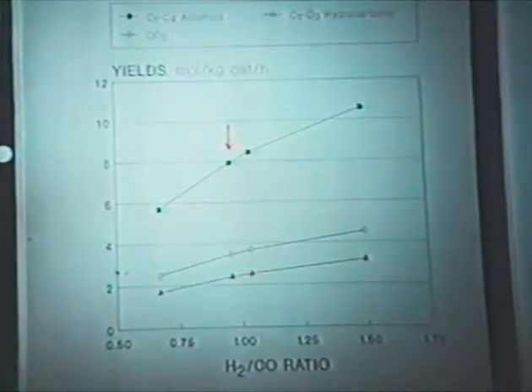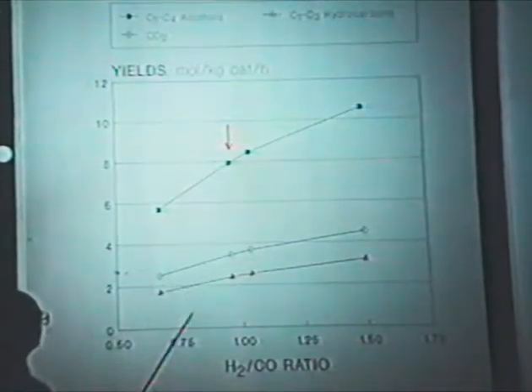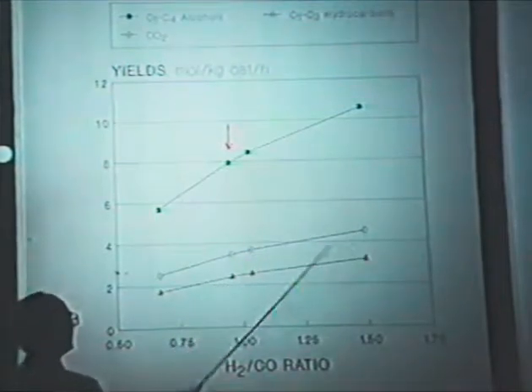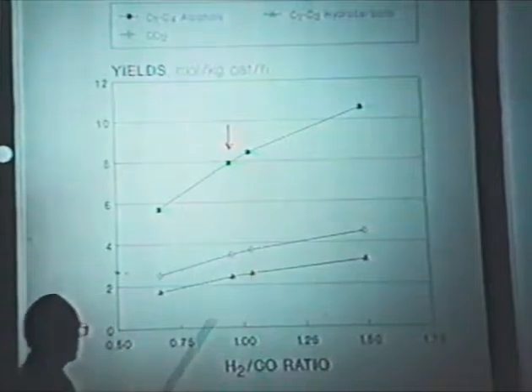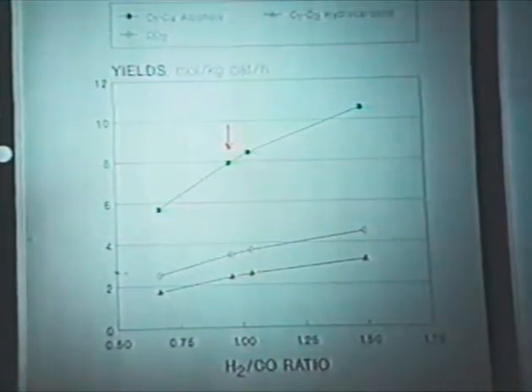And what this would indicate is that as we increase the hydrogen to CO ratio, the selectivity towards alcohol should be increased. So this would be one way, perhaps, to increase the selectivity towards alcohols. Other things that we've tested would be increase the pressure while decreasing the temperature. Those factors also would indicate that we should get a higher selectivity towards alcohols.